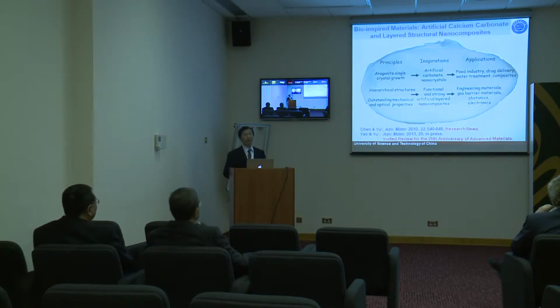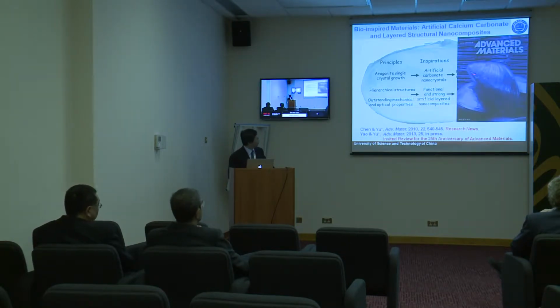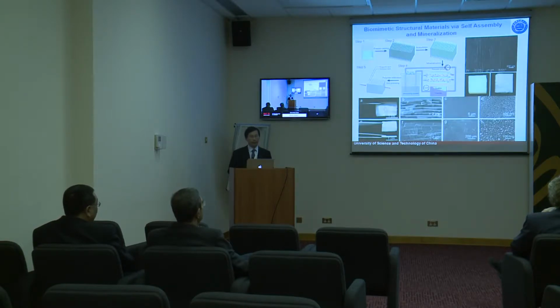This is nacre, a seashell. Is it possible? The answer may be yes, because this seashell structure is a multi-layer structure, with a very unique multi-layer structure you can see. So in the chemistry lab, we apply the freeze-drying technique to get these multi-layer polymeric structures. Then we do some chemistry here. Then we grow calcium carbonate within these multi-layer structures. Then finally, indeed, we can get this